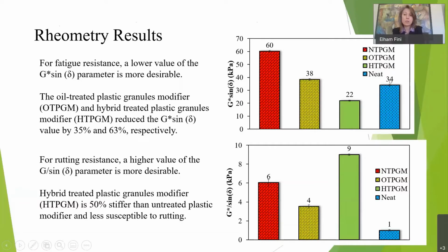So this is basically just what you use today on the road. And you can see this is 34. With plastic, with all the benefits that we will talk about with having plastic in, we just got 38, so very close. And here it says a lower value is preferred. So with the green, we even got a lower value than this. Of course, the red was way too high. I'm just putting the red here, even though it's rejected at the very first test, just to have a comparison and a benchmarking, but this won't be accepted because it's not compatible.